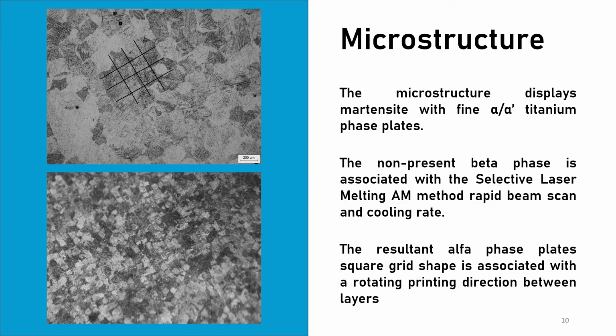Now, a microstructure analysis was also conducted on the samples. Martensitic alpha titanium phase plates were obtained. This is very common in the selective laser melting method due to the rapid beam scan and cooling rate. We can also observe the square grid shape in the microstructure. This is associated with a rotating printing direction between layers.